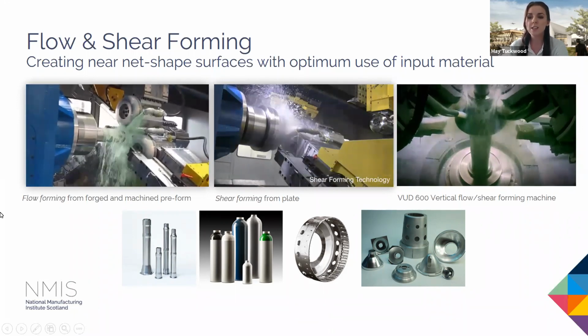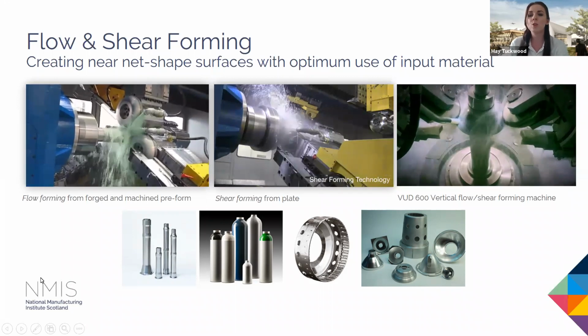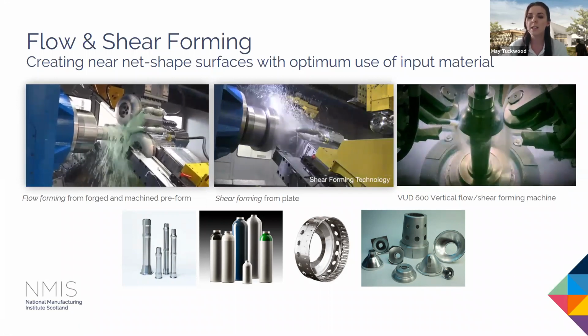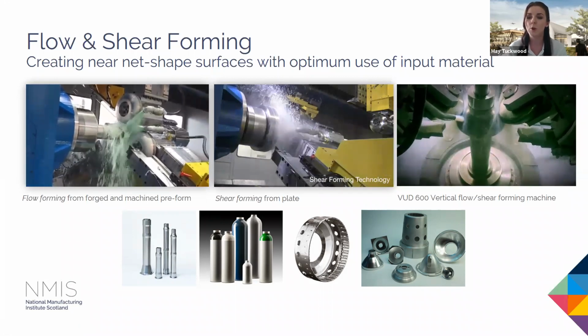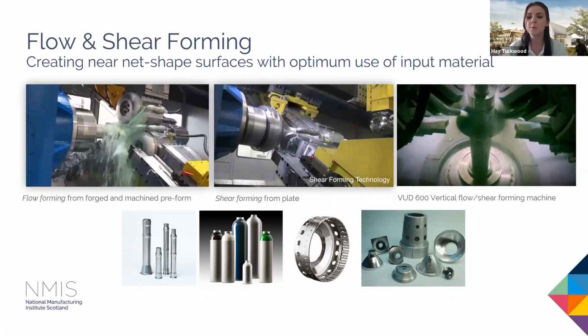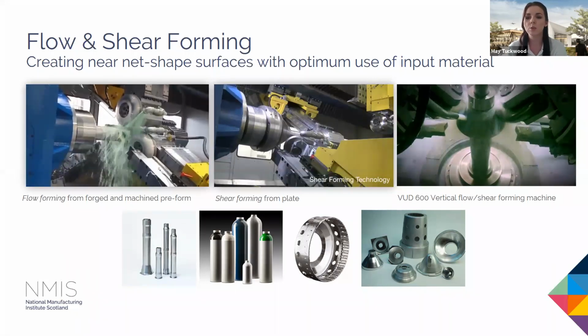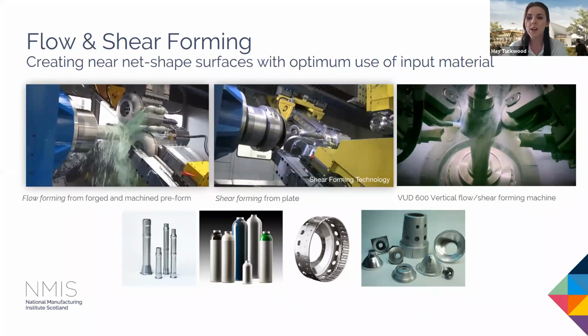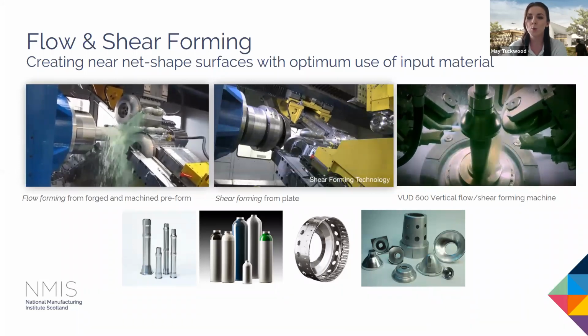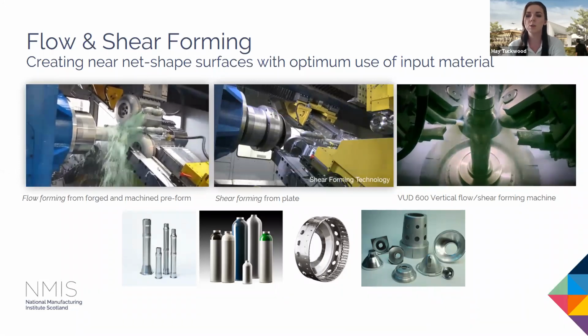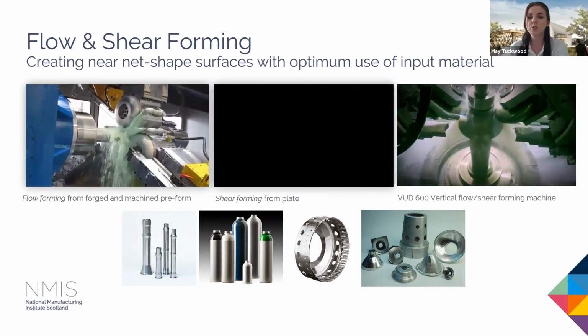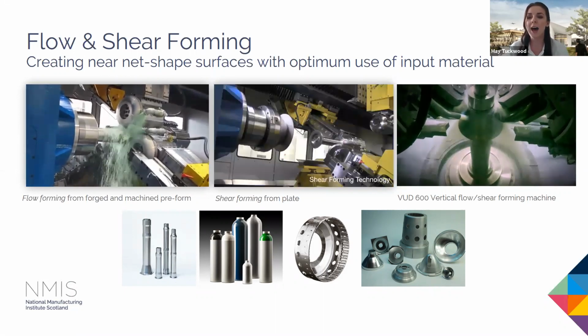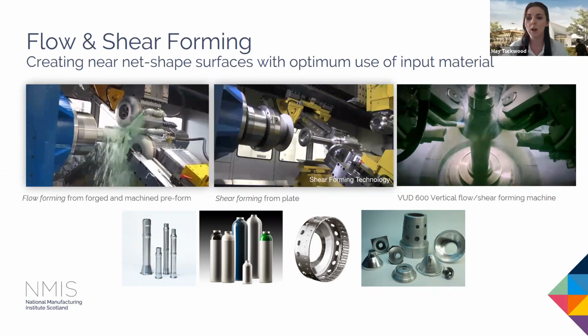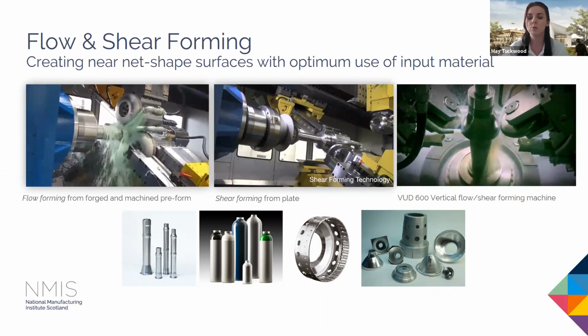So on the left here, you can see an example of flow forming. So if you're unfamiliar with flow forming, essentially we've got a forged and machined preform input. So we're starting with bulk material. We've got 3 large rollers here, each of which are offset to take their own individual portion of that starting thickness of material. Now what we're doing here is reducing the thickness and we've got axial displacement as those rollers move along the axis of the mandrel.